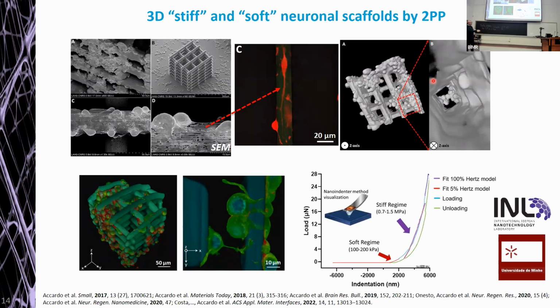And then the outer layer, which is just 2-3 microns thick, a softer Young's modulus in the range of 100 to 200 kilopascal, which is very interesting because that is the part with which cells are in contact and that the cells sense. And you must know that stiffness plays a role also in terms of stem cell differentiation, among the other things.